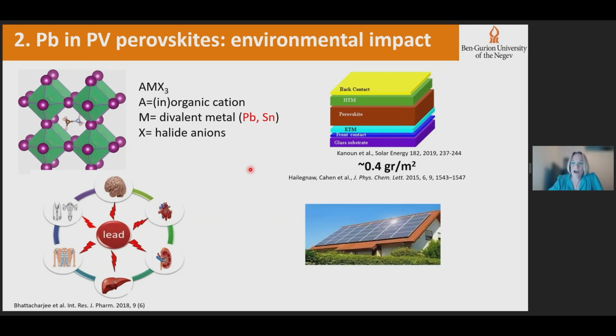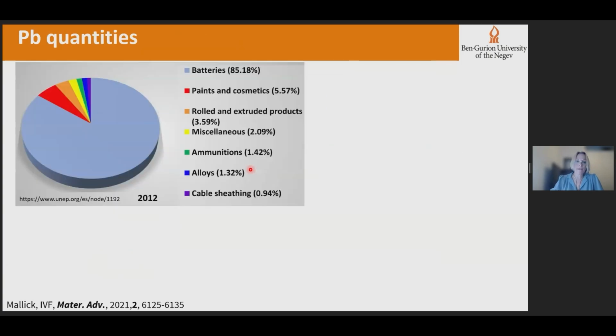Do you want to guess how much lead there is in silicon panels? Take a second. I hope you guessed right. It's more than an order of magnitude larger than the quantity of lead in perovskite solar cells, because there's always lead in the solder wires. If you look at the issue of lead globally, you would see that lead exists mostly in batteries. These are lead acid batteries that if you're not driving an electric car, you're probably using one of these. And that is responsible for about 85% of the lead in the world, such that even if we stopped using photovoltaics altogether or just perovskite, would probably make very little difference to the lead quantities used in the world.